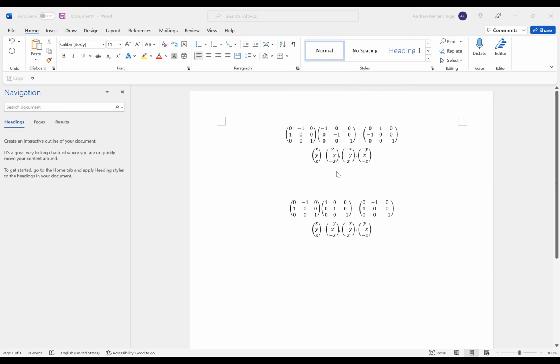So I did the same, but I took the fourfold rotation around Z, and now instead of inverting this structure with the inversion center, I mirrored it perpendicular to Z with this matrix to give you a different matrix. You see, it's a bit different. But if you multiply this 3 by 3 matrix by x, y, z, you end up with minus y, x, minus z.